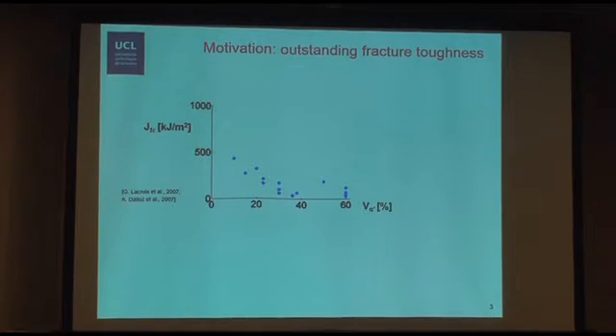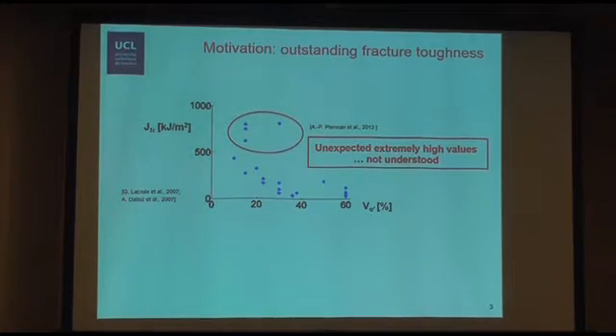However, amazingly enough, there are some DP steels with fracture toughness measured recently at UCL that far exceed the common values. It's those steels here. And the big difference of those steels is that they exhibit a plate-like microstructure. That's why I'm interested in morphology and why I'm working on those steels. Why it's so high and if it can be improved is something we do not know yet, that we would therefore like to figure out.